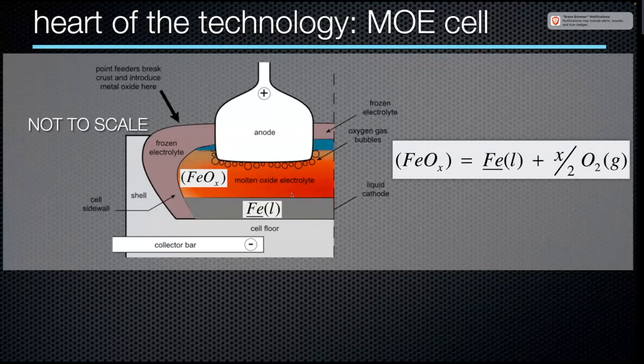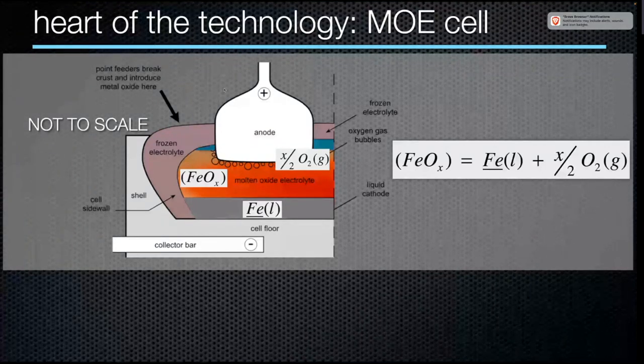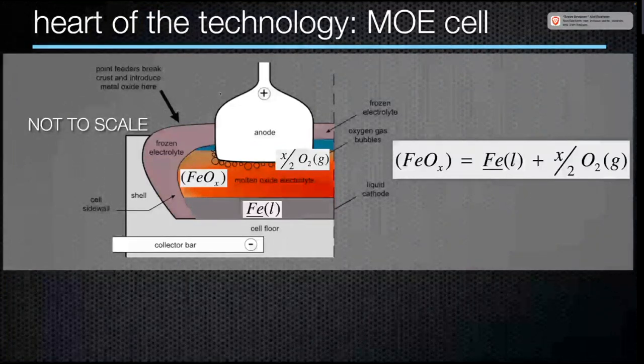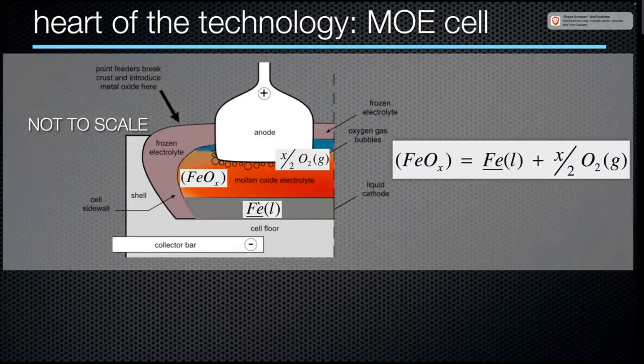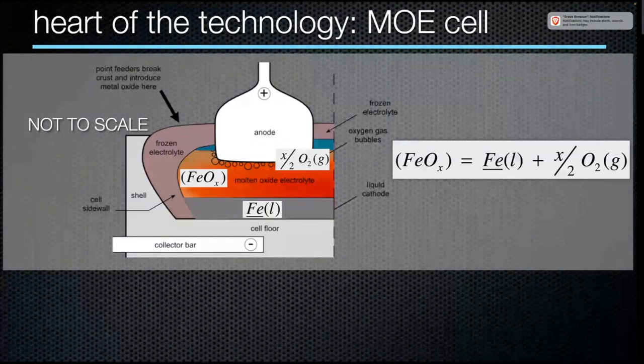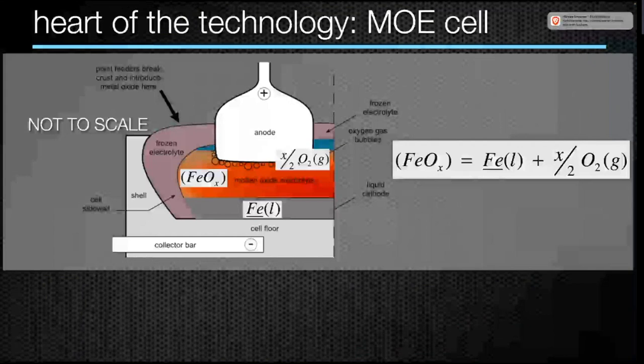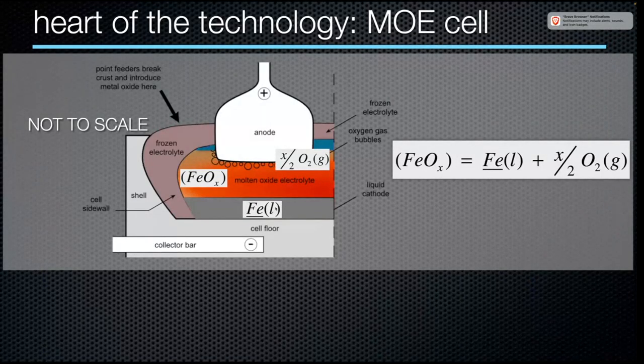And now at the other side, at the top, we take the oxygen and it evolves as gas bubbles on the anode. And then these gas bubbles rise to the surface, and then we can collect them and make tonnage oxygen. In point of fact, if you make a ton of liquid iron, you'll make about 2/3 of a ton of oxygen. That's on a mass basis. On a volumetric basis, if this cell is running at, say, 1,650 degrees Celsius, which is above the melting point of iron, the volume of the gas is about 16,000 times greater than the volume of the liquid. So it's a big management system.